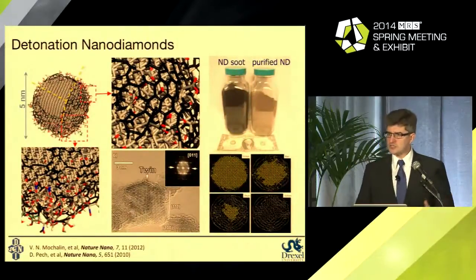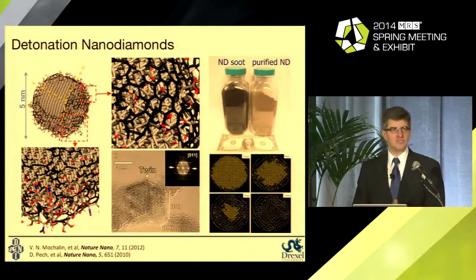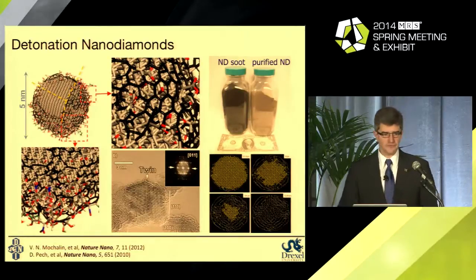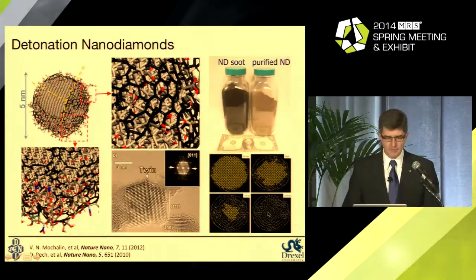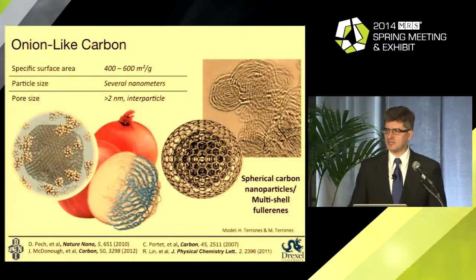And I already mentioned there are diamond particles. So sp3 carbon can also come in very small dimensions, about 5 nanometers, but they can be produced in a very simple way by putting explosive in a closed chamber and detonating it. What you do, you scrape diamonds off the wall of this chamber here. I'm not going to talk about diamond today in this presentation, but what is important, this material can be produced in larger quantities at moderate price, and by annealing it, we can transform diamond crystals to multi-shell fullerenes, which are called carbon onions. And then I will talk about application of those in electrical energy storage here.